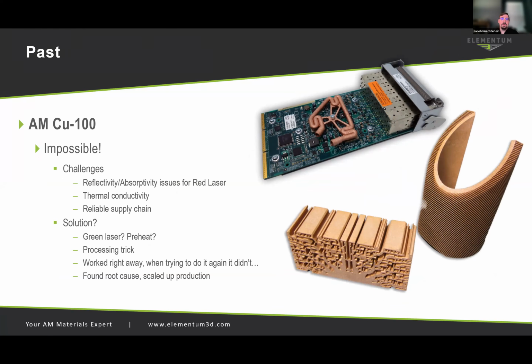And then from there, there were the challenges of, well, the conventional wisdom in the industry was, you can't print copper unless you have something like a green laser or something extra because of the reflectivity issues. So copper in general does not want to absorb laser power and laser energy. One of the advantages we found, though, was aluminum doesn't really either. Now, the advantage of aluminum is its lower melting temperature, but there's still that same problem of they both would like to reflect these particular wavelengths of energy. And therefore, the conventional wisdom was you had to go to green lasers to get this to work. That's really where I think we came in and said, well, hold on, that's not exactly true.